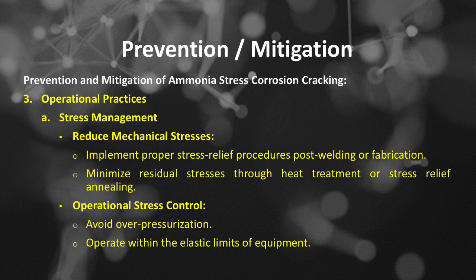Prevention and mitigation of ammonia stress corrosion cracking. Number 3 is operational practices, which includes: number A, stress management. Reduce mechanical stresses by implementing proper stress relief procedures post-welding or fabrication, and minimize residual stresses through heat treatment or stress relief annealing. The second is manage operational stress, control and avoid overpressurization. Operate within the elastic limits of equipment.